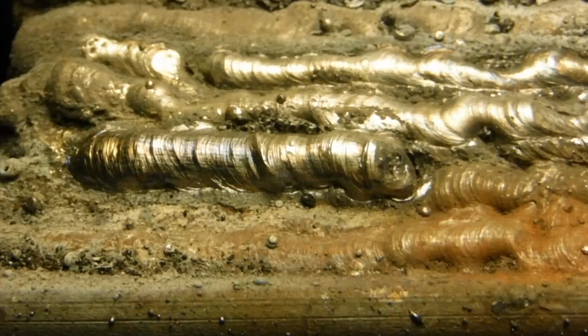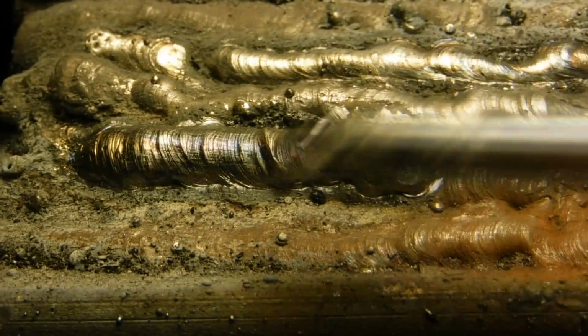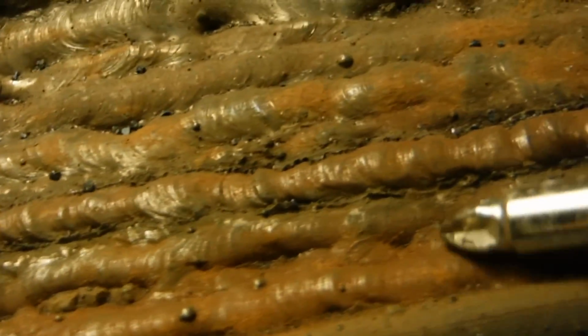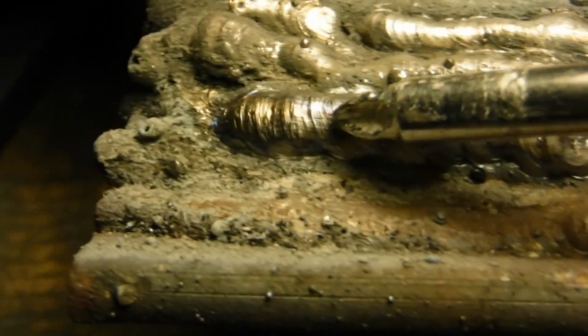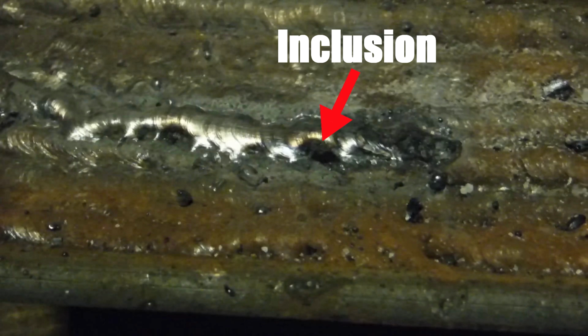In this footage here, you can see exactly what the end results of the weld look like. Some other complications of going too slow is that some flux can make its way back into the weld. This is called an inclusion. An inclusion is a little bit of slag nestled inside of the weld itself. These drastically weaken the strength of the weld and can be difficult to remove. Going too fast, however, can result in an equally as weak, stringy weld like shown in the background footage here.